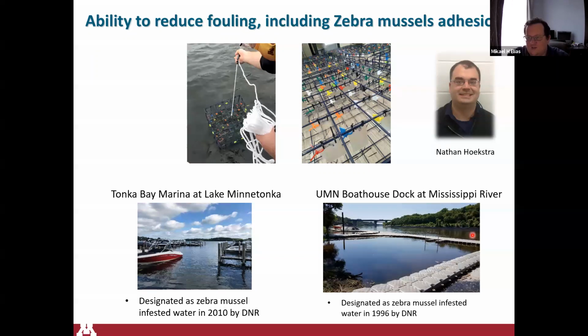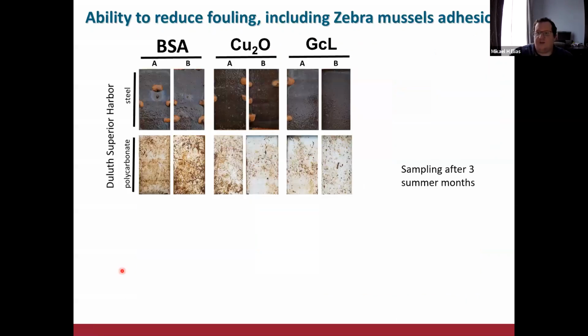And Nathan has been performing some of these experiments where we use coated pieces. These are polycarbonate, but we've used a variety of different substrates here. And we submerge those samples in these sites and we sample them at different times. And so some of the results here that we could obtain. So this is still the Duluth Superior Harbor, 2 different materials.